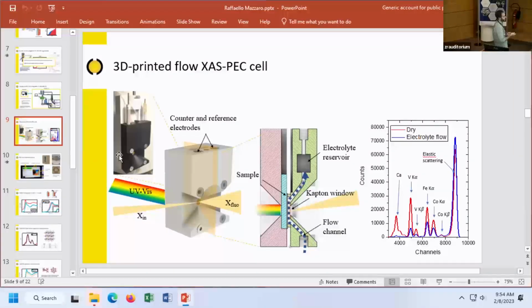And the final thing we needed to think about for the design of this cell was that we need to work in flow conditions. So we need to flow the electrolyte in the electrochemical cell, as basically we are working with an oxygen evolution reaction, which produces a gas on the surface of the electrode. As soon as we produce a gas, we start having bubbles, and that is changing the attenuation coefficient of the electrolyte during the experiment itself. So basically, we have unreliable absorption data.